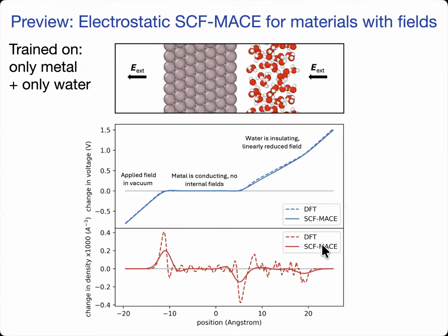We're also moving into a more explicitly self-consistent model where you don't just do 2 iterations of charge distribution, but actually run that loop to full self-consistency. And when you do that, you can do cool things like interfaces, metal insulating interfaces. Here's a model that's trained on an aluminum slab and external fields, and separately on a water slab and external field. And when you put the 2 together and put an electric field on, you see the correct behavior.